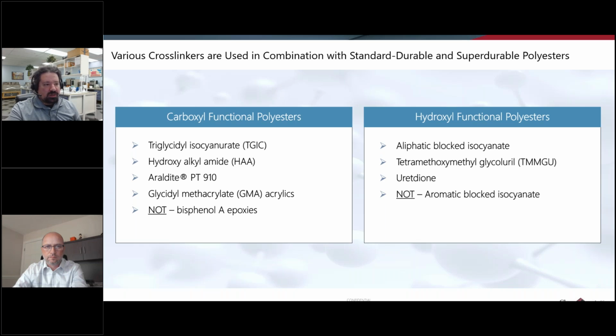A variation on the blocked isocyanate is the uretdione. They call it blocking agent free or self-blocked, but essentially they have a weak ring on the isocyanate. So instead of having a chemical or a substance that disappears and gets pulled out into the stack, uretdione just unblocks itself when you hit a certain temperature. And by temperature, blocked isocyanates with the blocking agent are typically around 170 C. The uretdiones might be 160 C, although I think they've developed catalysis methods to get it lower than that.